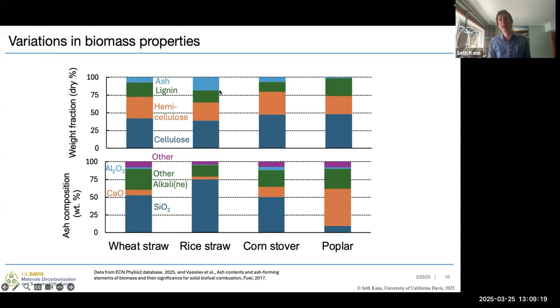When we look at the composition of that ash, which is going to be important for using these materials in concrete, we can see that relative to the other materials, the rice straw really has a lot of silica content. That'll give it some pozzolanic reactivity in our concrete. And in contrast, there is very little ash in our wood-based materials, but a higher percentage of that ash is calcium than in those other materials.